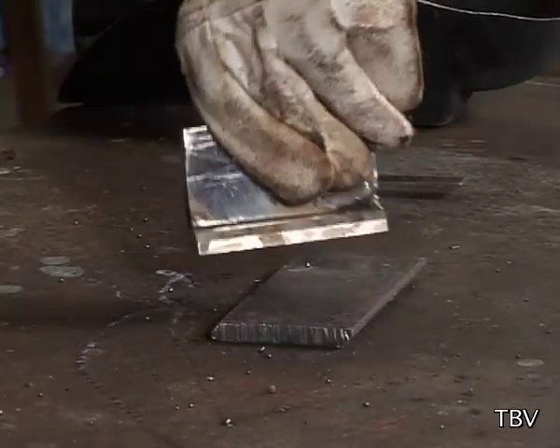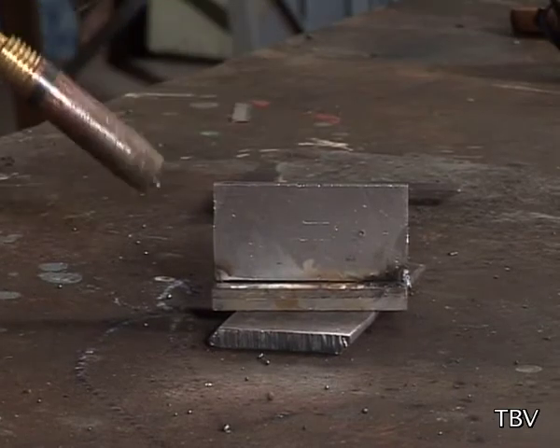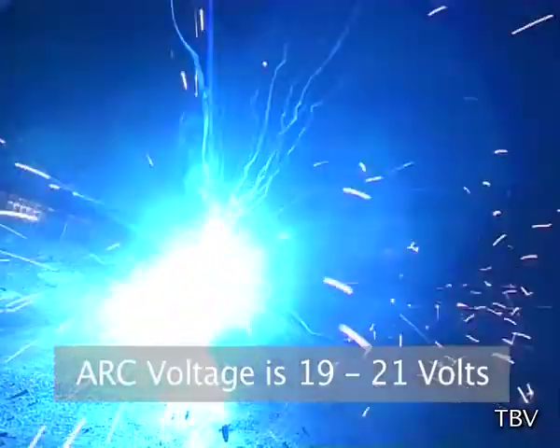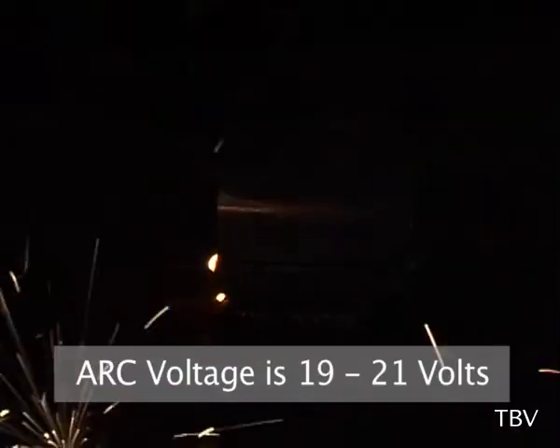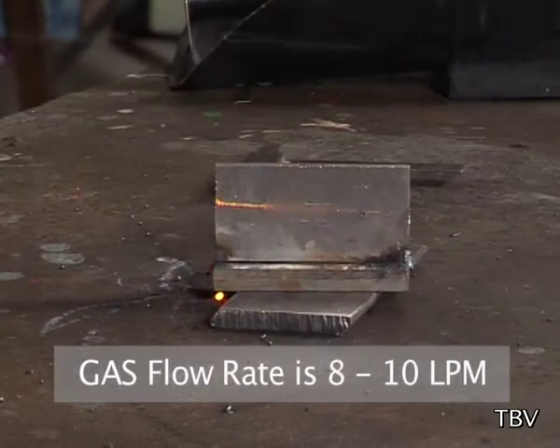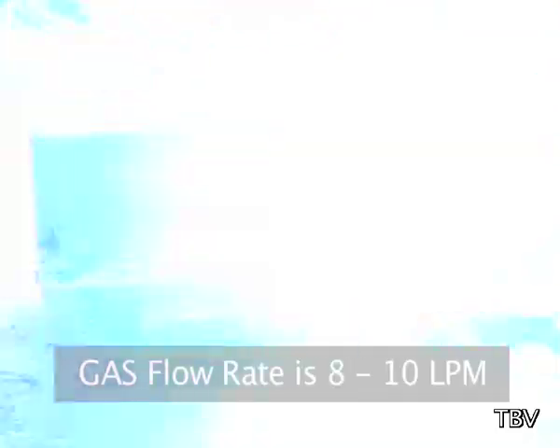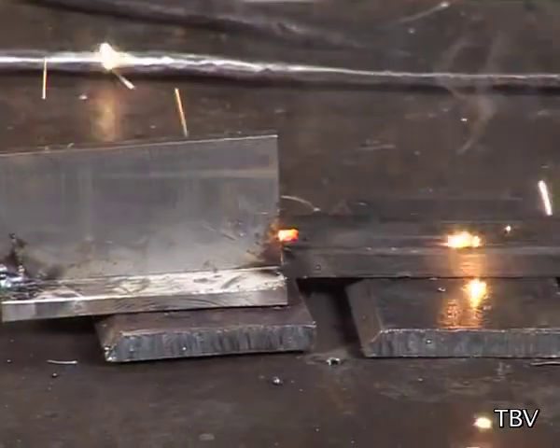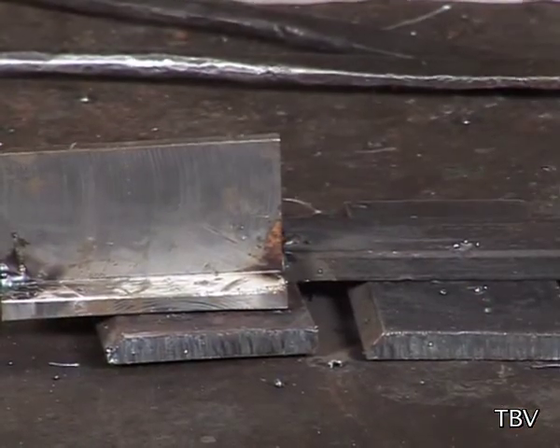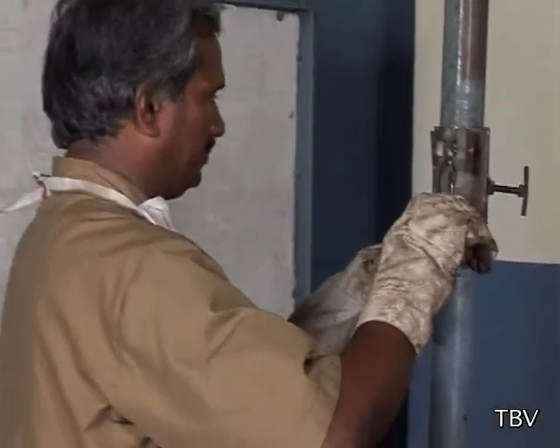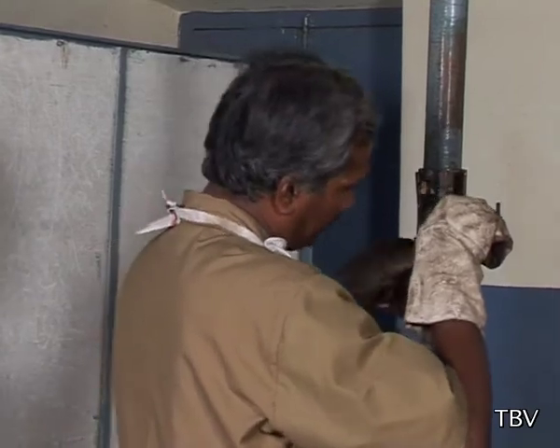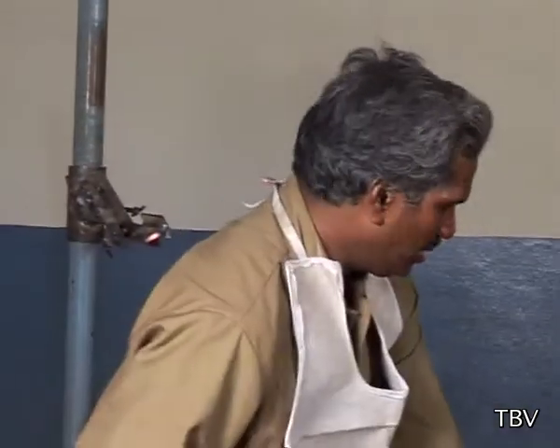As seen earlier, for 0.8 mm wire, the arc voltage is set at 19 to 21 volts and the gas flow rate at 8 to 10 LPM. When the plates are ready, mount the plate such that the plate is vertical and the scribed lines are in horizontal position using the job positioner. Feed rate is set.